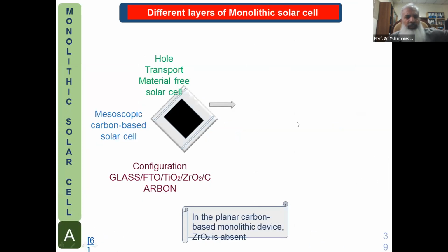We have recently been working on the fabrication, characterization, optimization, and simulation of hole transport material-free perovskite monolithic solar cell. And many companies are providing prefabricated components at different levels of this technology. One can buy prefabricated glass, FTO, titania, zirconia, carbon electrode, and then they can infiltrate perovskite and provide heat treatment, and the cell is ready within about 1 to 2 hours.